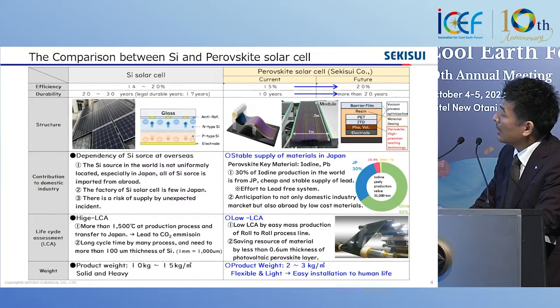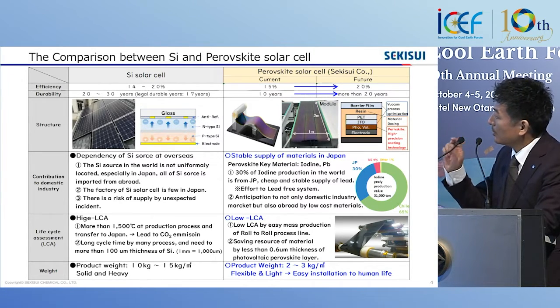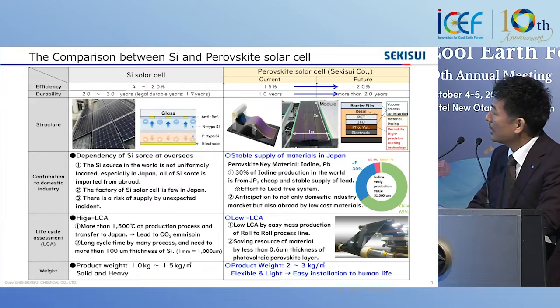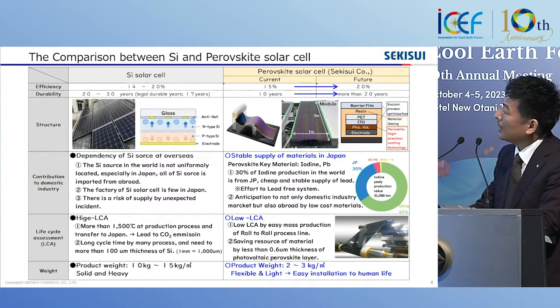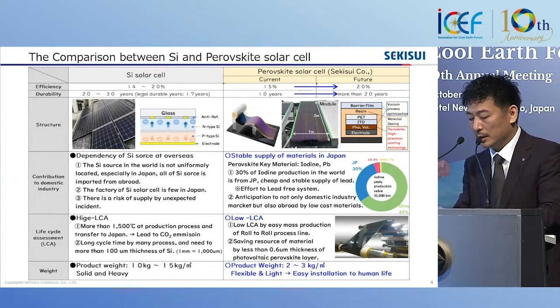We are also thinking about life cycle assessment, low-cost LCA, and first, low LCA through easy mass production, the roll-to-roll process at Sekisui Chemical. This is very easy and low cost, and saves material resources, because the perovskite active layer is less than 0.6 micron thick, so very thin, 600 nanometers. This is a very important point: our perovskite solar cell is very light, 2 to 3 kilograms per square meter, and flexible. We are thinking about easy installation in human life, in the city, and in any place.